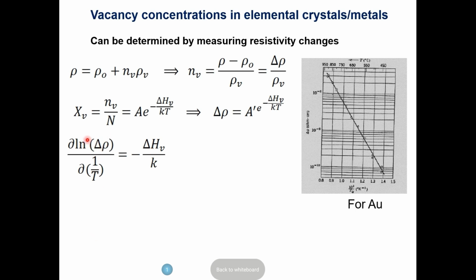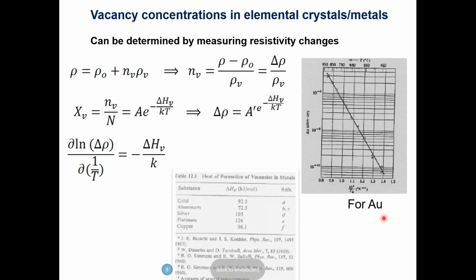Here is some data for gold, for example. You can see these open circles are the actual experimental data, and it fits very nicely in a straight line. You calculate the slope, and that tells you the enthalpy needed to create a vacancy in gold. I'll show you some numbers.